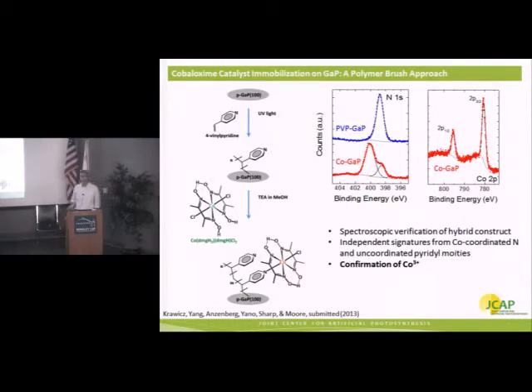This is another hydrogen evolution catalyst of a cobalt-oxime class. It starts off in a configuration such as this. Following reaction with the pyridine, you have displacement of one of these axial chloride units and binding of the pyridine to the catalyst. Again, we can verify that we've created what we set out to create using surface-sensitive spectroscopic methods. In this case, XPS.